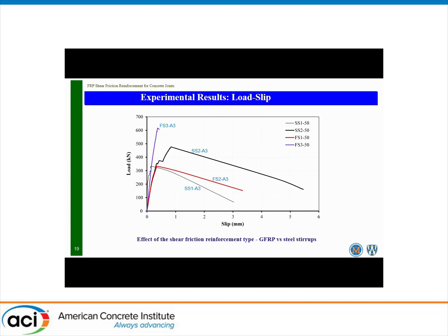The specimen reinforced with 2 steel stirrups showed a higher load, but compared with the specimen reinforced with 3 FRP stirrups, the ratio between the stiffness of the reinforcement may be 3-4 times higher for steel than FRP. On the other side, the FRP specimen still carried or showed much higher capacity, attributed mainly to its perfect linear behavior. Once the steel specimen hits the yielding strength, there's no source for that clamping stress - we've already developed a lot of lateral strain and lateral separation dilation of the specimen, and it failed suddenly, which was not the case with the FRP stirrups.